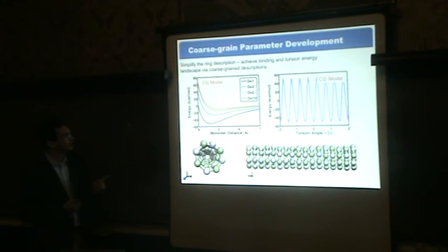The one thing you can find with these simulations is that if you use typical Lennard-Jones type interactions and so forth, we don't get shear rigidity. In the case of actual nanotubes, electrostatic interactions really give the shear rigidity to the material, because as you try to rotate it, you don't have the same alignment of charges that you have with hydrogen bonding. So with this kind of simplistic model, we think that we can at least get the shear rigidity and the elastic modulus correctly, and then that would help us predict the persistence length at longer length scales, and also the conjugation of the hydrogen bonds in the formation of the nanotube.